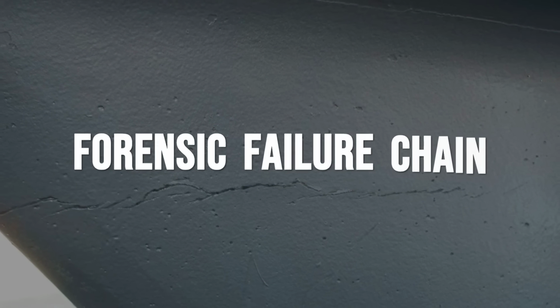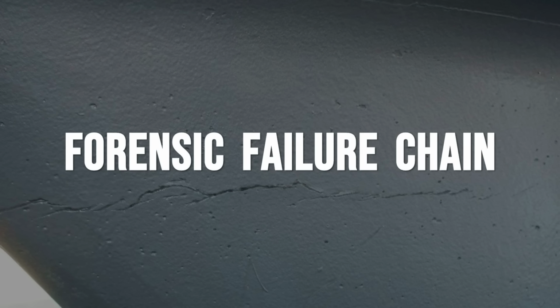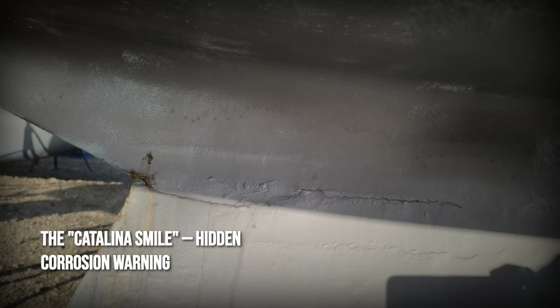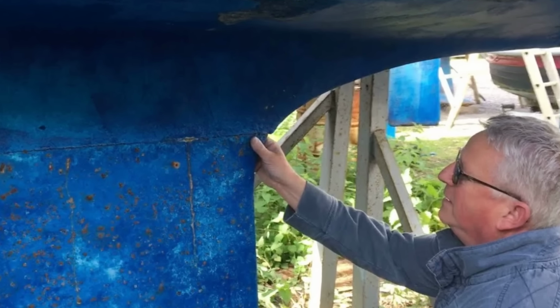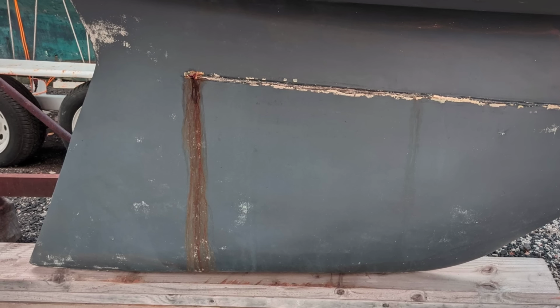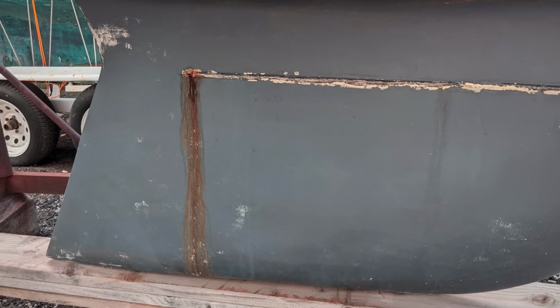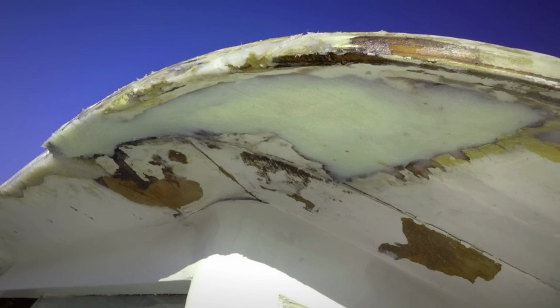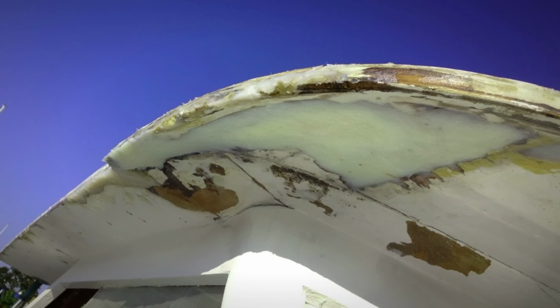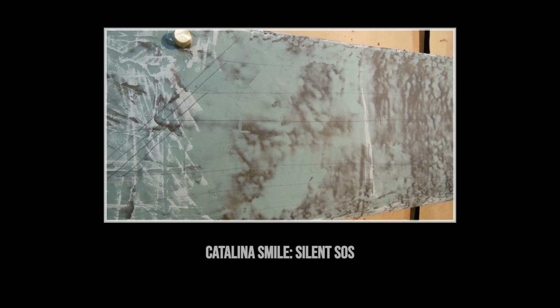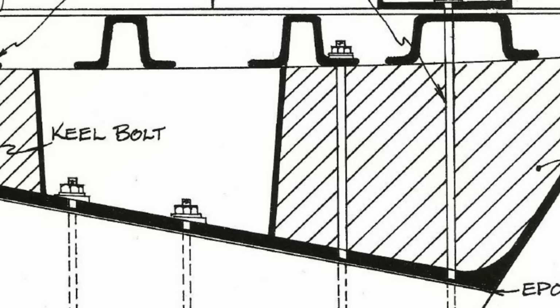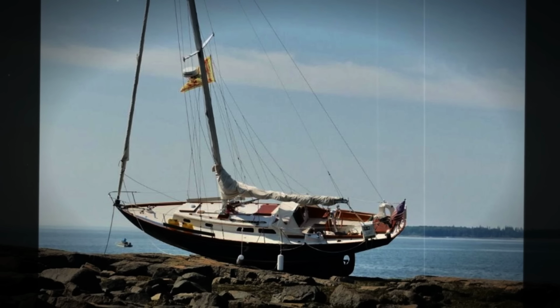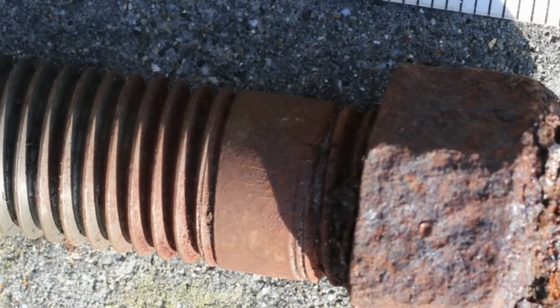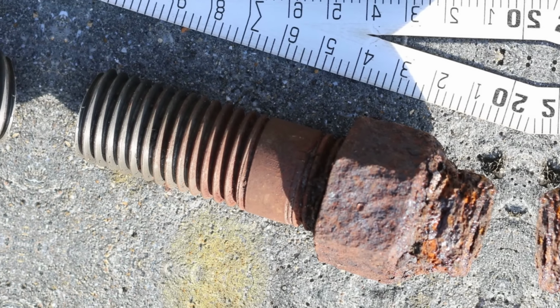A hairline crack running along the front edge of a keel joint does not look like much at first glance. On the yard floor, it is called the Catalina Smile. Surveyors know it as the warning sign, a subtle curve at the seam where the keel meets the hull, sometimes barely visible, sometimes wide enough to slip a credit card into. This crack forms when the keel moves ever so slightly, flexing against the hull stub. Years of pounding, a hard grounding, or simply the slow march of time can start the process.